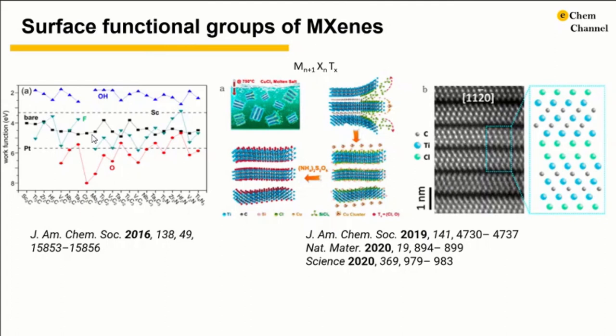Based on DFT simulation, surface chemistry is found to have strong effects on the Fermi level of MXenes. O terminations always increase the work function with respect to the bare surface. OH always decreases it, whereas F exhibits either trend depending on the specific material. The relationship between surface chemistry and the work function, conductivity, transition to superconducting states, magnetism, and energy storage capacity of various MXenes has been established. For example, the oxygen terminations exhibit the highest theoretical capacity for proton and lithium ion intercalation. Hence, it is crucial to control the surface functional groups of MXenes.